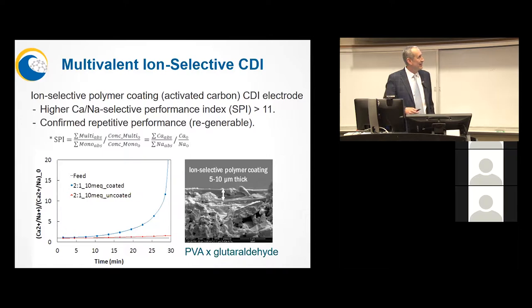And already we're seeing a preferential removal of calcium to sodium of about 10 to 1. So that way you don't waste your absorption capacity on sodium and you focus in more on this multivalent cation. So this is very early work. Most of what I'm showing you is relatively early, and it looks promising, but of course it's not demonstrated fully.